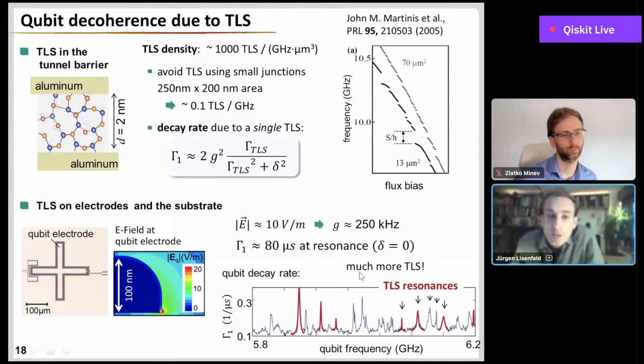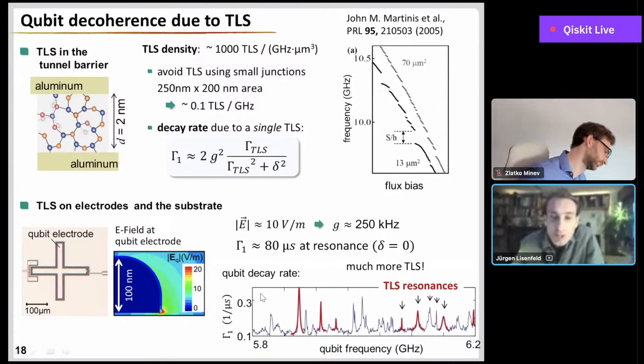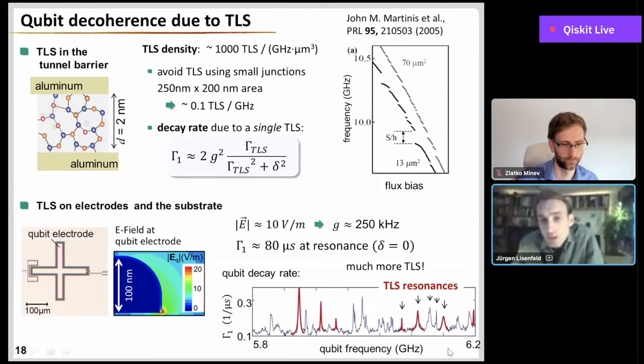And you can actually see those defects if you just measure the energy relaxation rate of the qubit as a function of the qubit frequency. And then you see there's a certain base level here, which in our case corresponds to 10 microseconds T1 time. But at certain frequencies, you have a much enhanced energy relaxation rate. And some of these peaks here, I colored in red, these now reveal the individual resonances of these defects, which follow this Lorentzian resonance curve here.